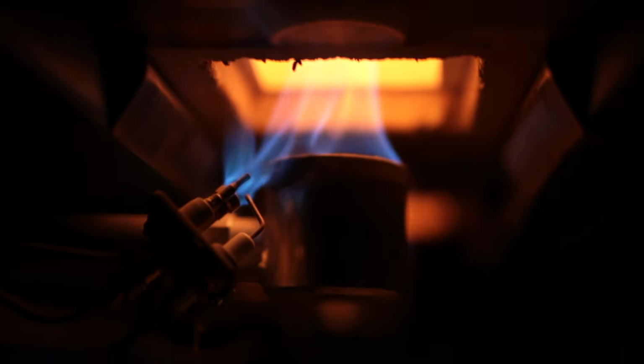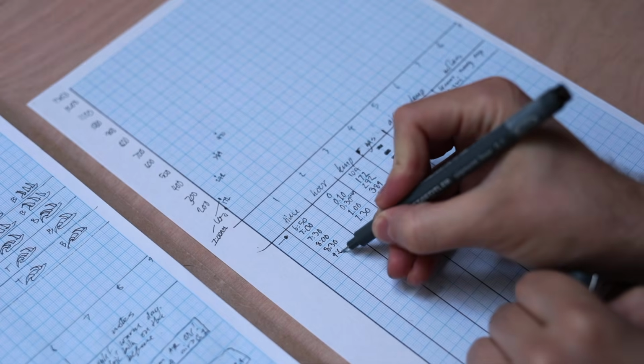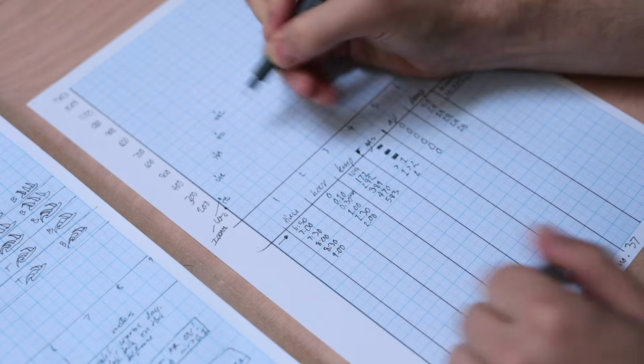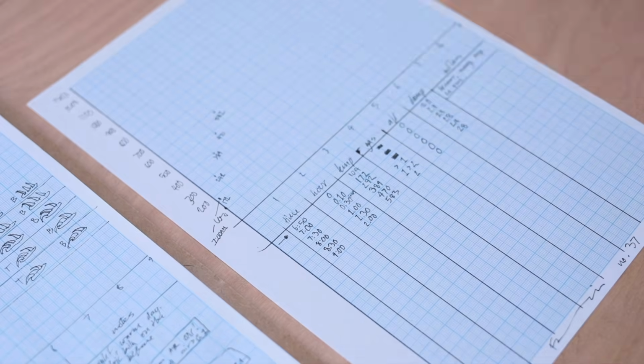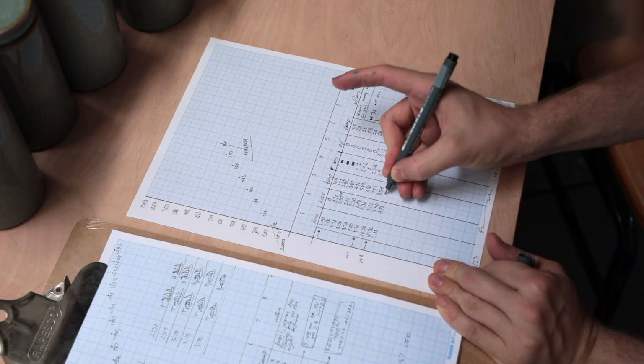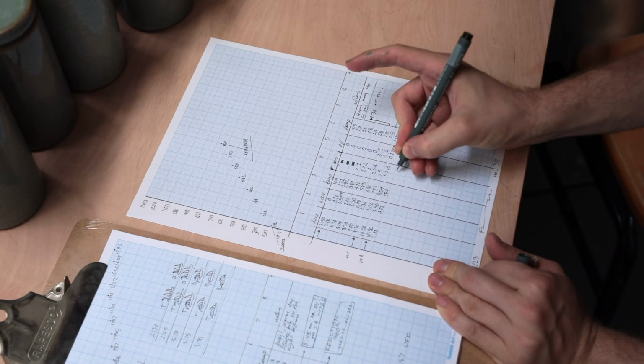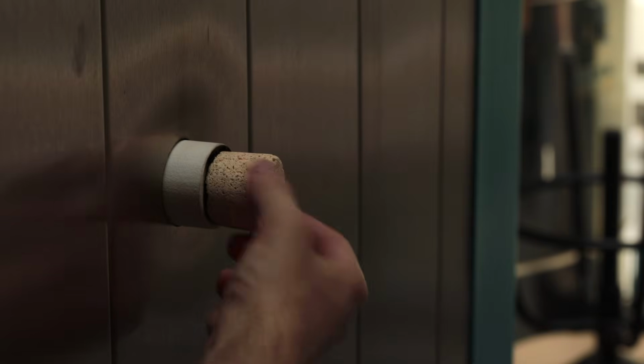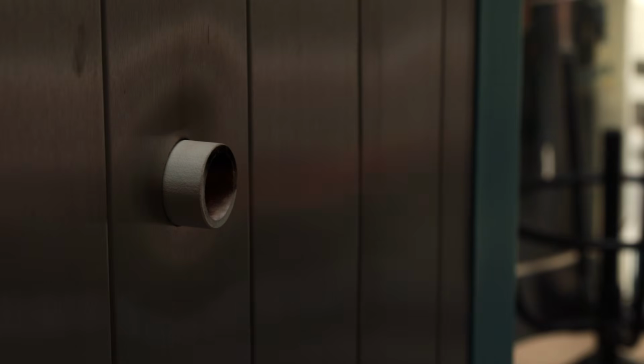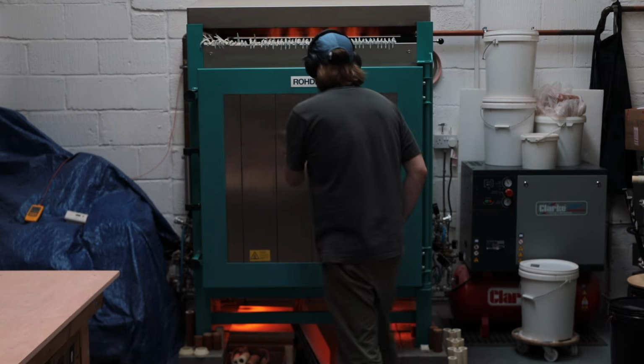This process is entirely manual, and the firing itself takes about 8.5 hours. The gas and air pressure and the damper position are all changed by hand, and all of these need to be worked harmoniously for the temperature to rise properly whilst maintaining a strong reduction. And one sure sign that a reduction is taking place is that you'll be able to see flames popping out of the spy holes and jettisoning out of the flues in the back.